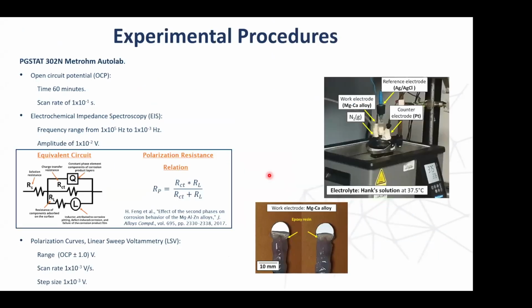And also we tested the corrosion in the Hanks reagent, which is the simulated bodily fluid electrolyte. And this electrolyte we tested in an electrochemical cell. We control the temperature with a double boiler. And we have the setup here to carry out linear sweep voltammetry and also electrochemical impedance spectroscopy.